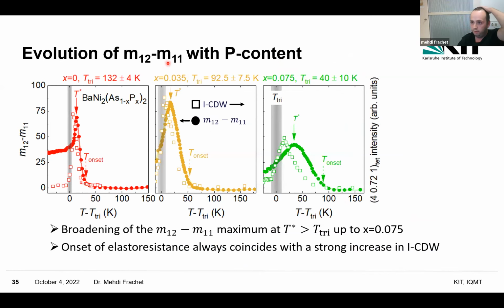So this is the evolution of this B1g elastoresistance coefficient with phosphorus content. So this is plotted as a function of temperature minus the triclinic transition temperature. Okay. So the circles are the elastoresistance coefficient, and the squares are the intensity of the incommensurate charge wave. And what you can see is that for up to 7.5%, this maximum of the B1g elastoresistance broadens with phosphorus content, but it always occurs slightly above the triclinic transition temperature. And what we can notice also is that the onset of this elastoresistance always coincides with a strong increase in the intensity of the incommensurate charge wave.